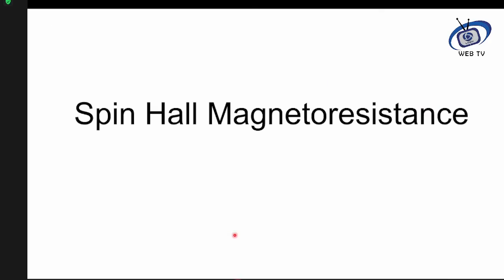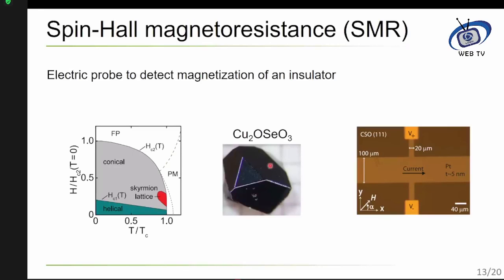Now, I would like to introduce how we can detect these different types of magnetic structures by a magnetoresistive method. Magnetoresistance is a typical name used whenever the resistance of a material changes with an applied field. Then we call it magnetoresistive. Spin Hall magnetoresistance is a little bit unique. What we do is polish this crystal and put a very thin platinum metal on it. Platinum is very special. It's a very heavy metal and carries very strong spin orbit coupling.